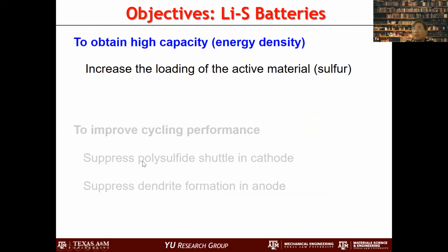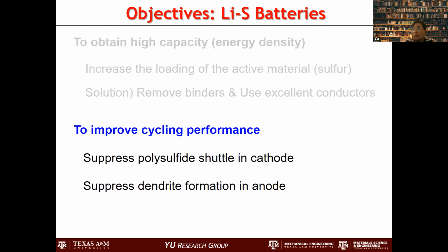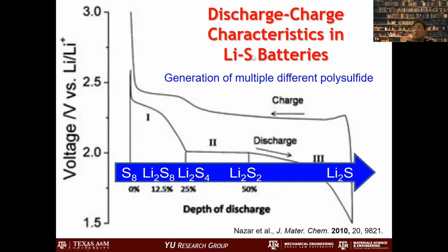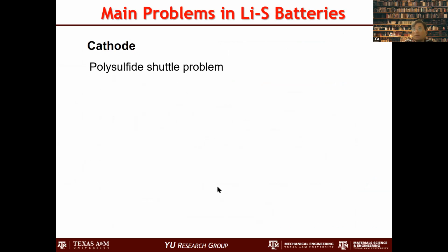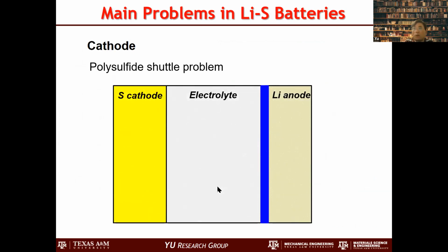So, and then this can solve the problem, and I'll show you a little bit more detail later. And another thing that we are trying to improve here is the cycling performance. This is a discharge curve of a lithium-sulfur battery, and the discharge and charge are all different here. And these materials in between are actually soluble in the electrolyte, and they're moving around everywhere. And some of them actually get lost, and this is problematic. This is what we call the polysulfide shuttle problem.